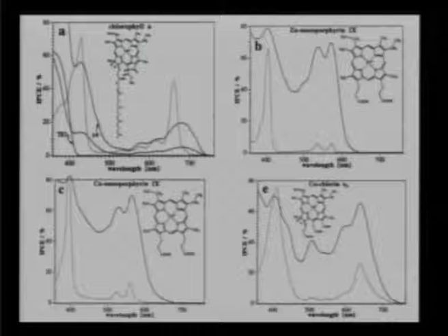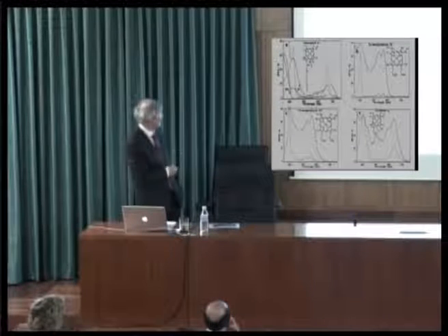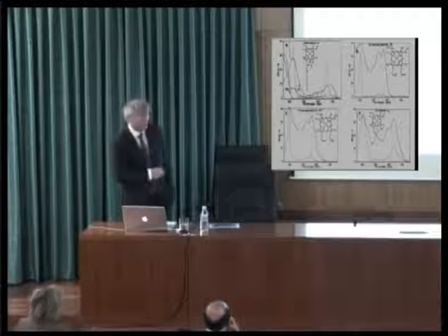And so if you use chlorophyll as a sensitizer, we get 20% on the Q band of incident photon to current. That's not bad, but of course that's not what you need. In the Soret band, you get a little bit better. But look at this. If we take our best, these mesoporphyrins, very simple molecules, over 70%. Some in the Soret band, over 80% conversion of incident